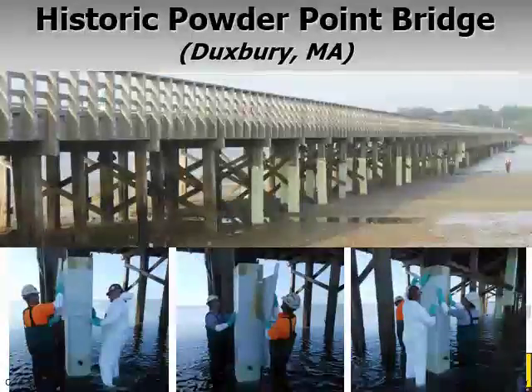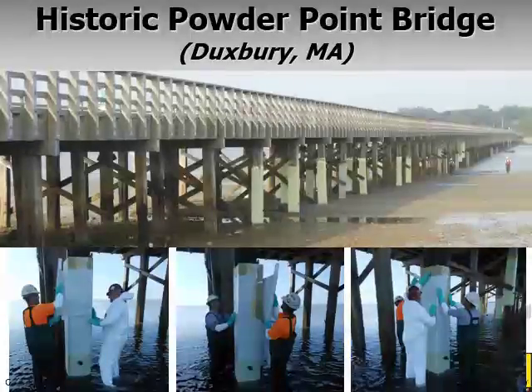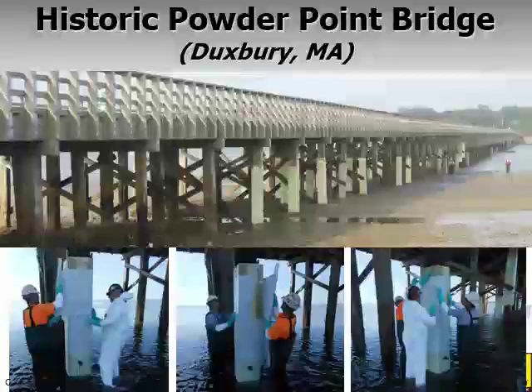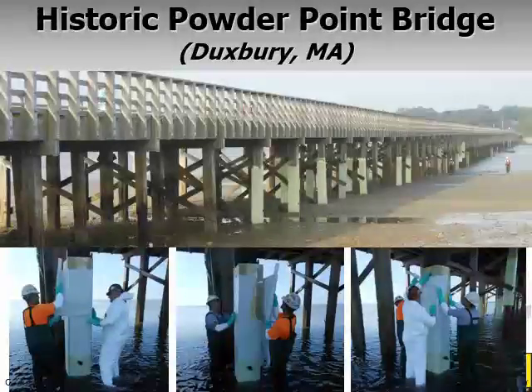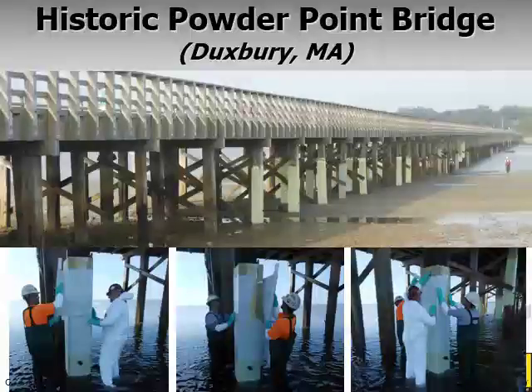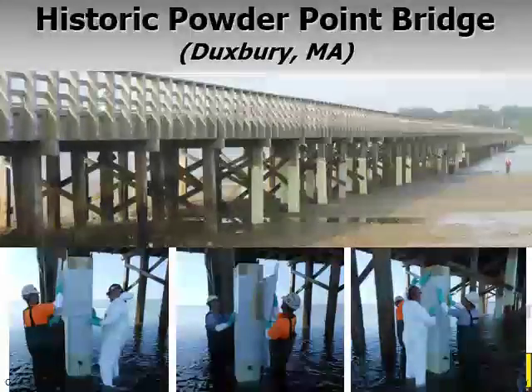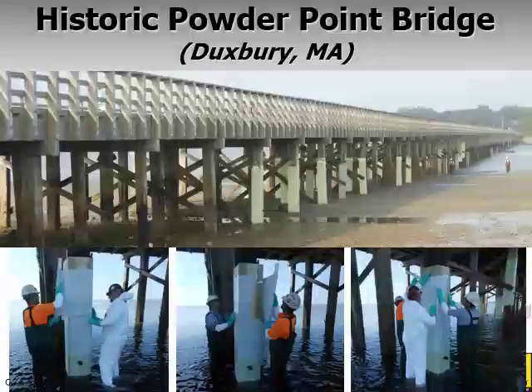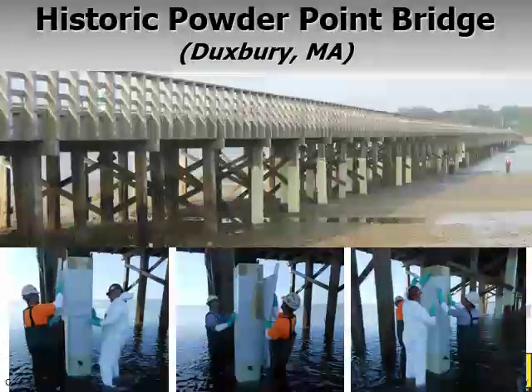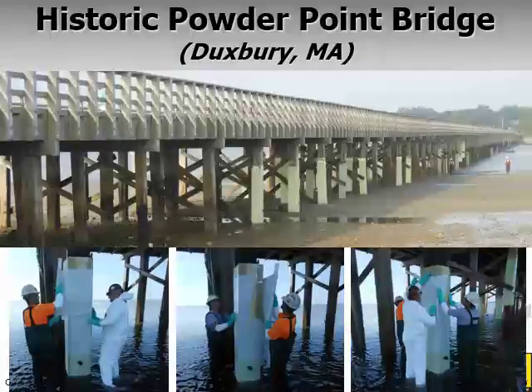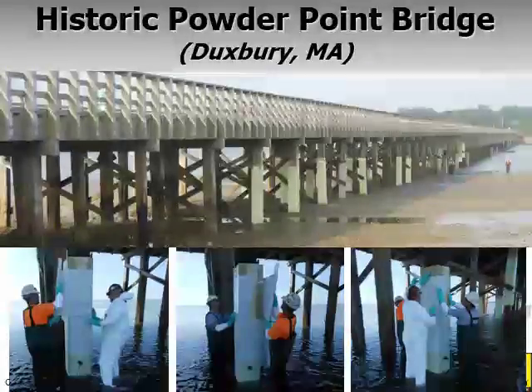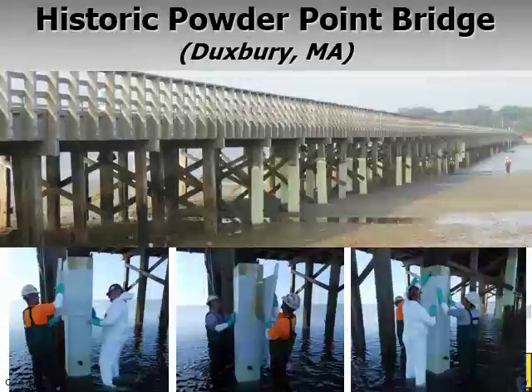But the confinement then is provided by wrapping continuously one or more layers of fabric around that prefabricated shell. And once we do that wrap to provide confinement, that then becomes a part of our patented system. And then this entire assembly can be pushed up or down. When it is in its final position, a grout can be introduced, as you see, through those ports at the bottom of those jackets, and that grout will bond the shell or jacket to the host column or pile.